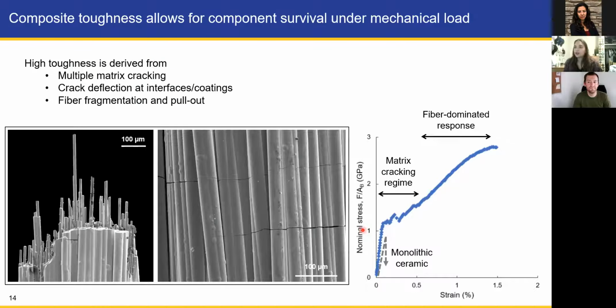Okay, so in terms of the mechanical behavior, which is what we introduced before in our force displacement curves, we can also create stress and strain curves. What we get, as a reminder, for monolithic ceramics is very brittle failure. So this linear regime, and then we break at very low displacements or strains. But these composites are so interesting because you can see the ductility that they have compared to regular ceramics.